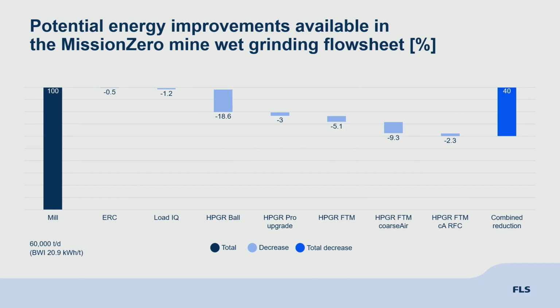So if you look around the whole flow sheet, we managed to reduce the energy by 40% just by putting our new technology in. But this was on a desktop study. We repeated this for dry grinding, and the result we got for dry grinding was a 60% reduction. However, we were not confident in the dry grinding in terms of the classification for coarse flotation, which I'll take you through in a little bit.